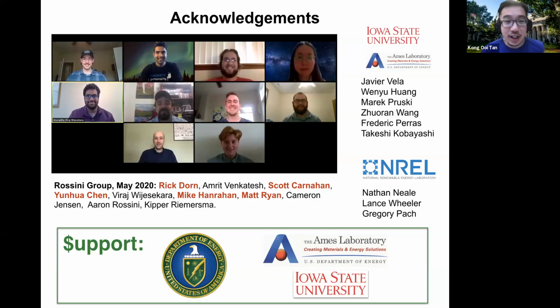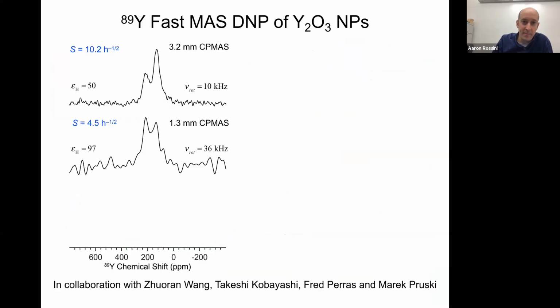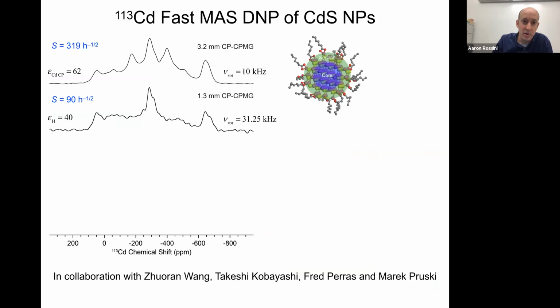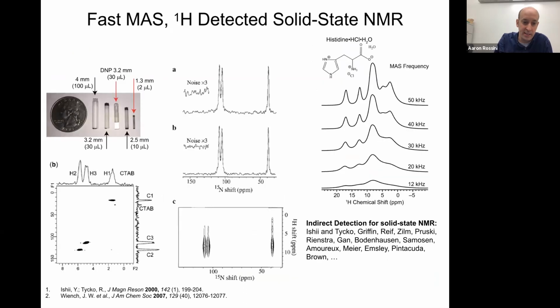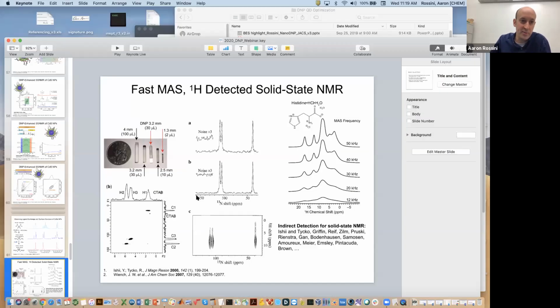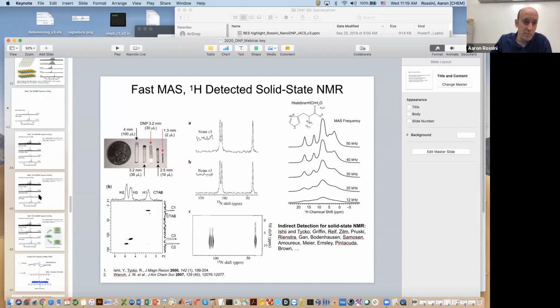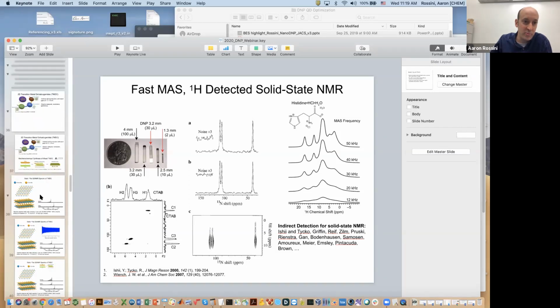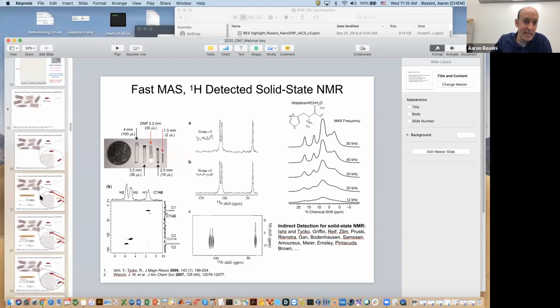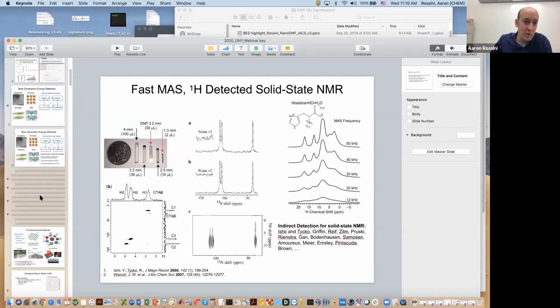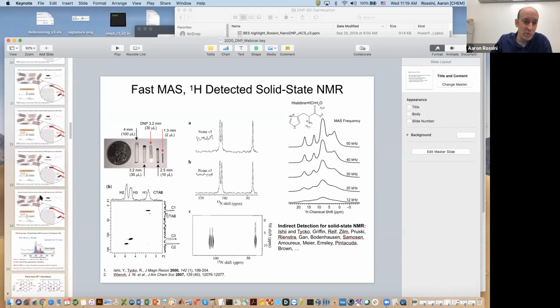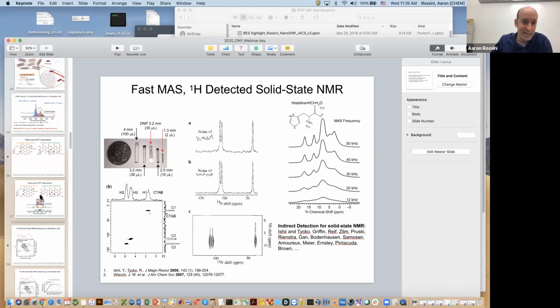If you have unpaired electrons in the mixed selenites, does that not reduce the very long T1? Yeah, it does. For the ball milled sample and the annealed sample, we can actually reduce the delay that we use to acquire the spectra. I think my student was able to get a spectrum with a 1 second delay. But the problem is you also get a big hit on the T2. And so that kind of makes it difficult.